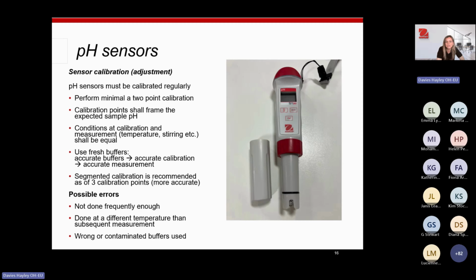The conditions at calibration and measurement should be equal. So you should always measure your sample and calibrate at the same temperature. Make sure your solutions are at the same temperature. What that means is, if you keep your calibration solution in the fridge, take it out of the fridge and bring it up to room temperature, the same temperature as your sample, just for accuracy. Always use fresh buffers, because accurate buffers equals accurate calibration, and that's accurate measurement. And if at all possible, 3-point calibration is always recommended, but a minimum of 2 points should be good.